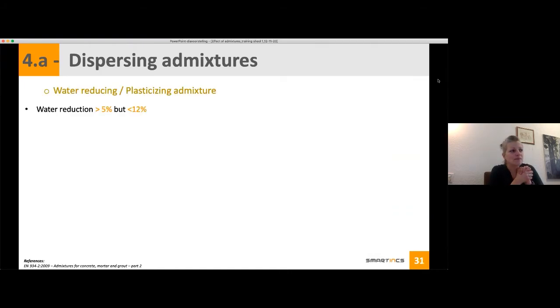If I first look at plasticizing admixture, they are also classified depending on the water reduction they bring. For water reducing or plasticizing admixture, you should think of more than 5% water reduction and less than 12%. Dosage is also very low, 0.1 to 0.4% of cement. If you compare different products, you should always be careful about the concentration of the solution, because not all admixtures have the same concentration. Some are 40% and some are 20%, which means that the end dosage can be different.